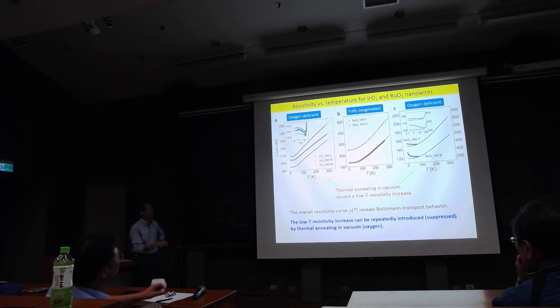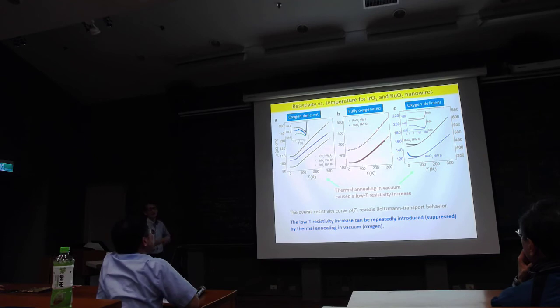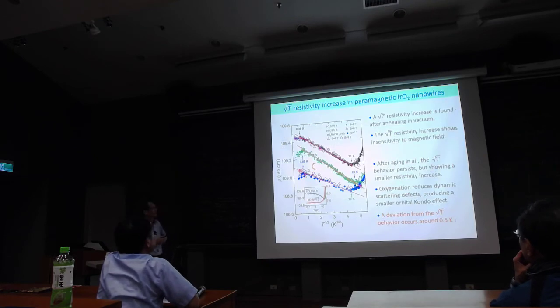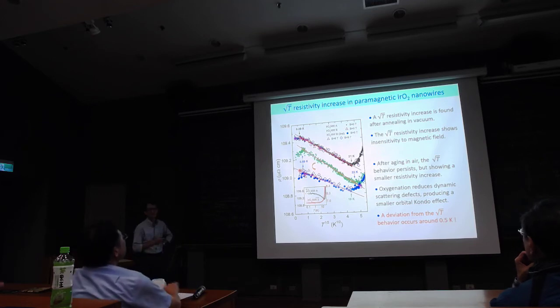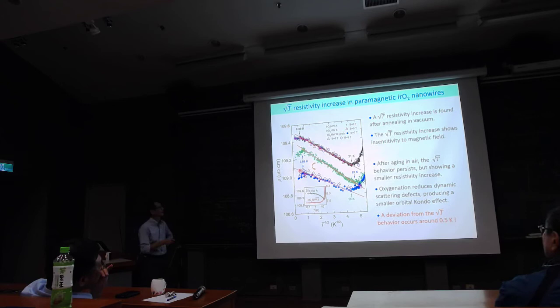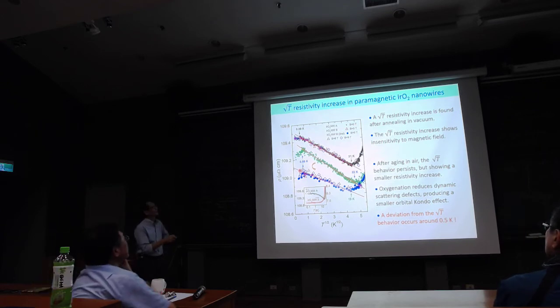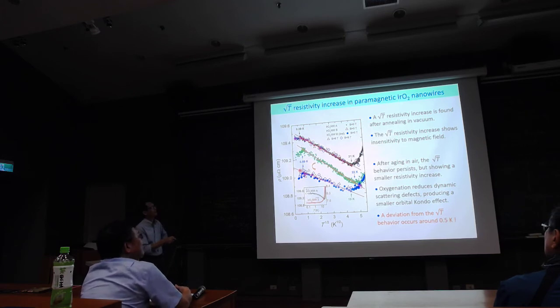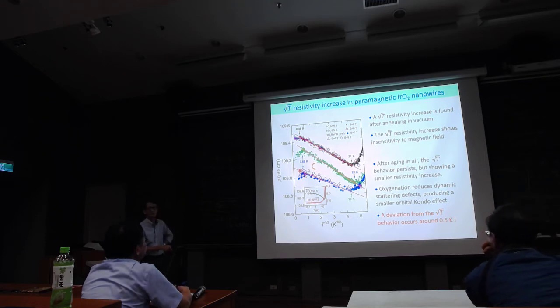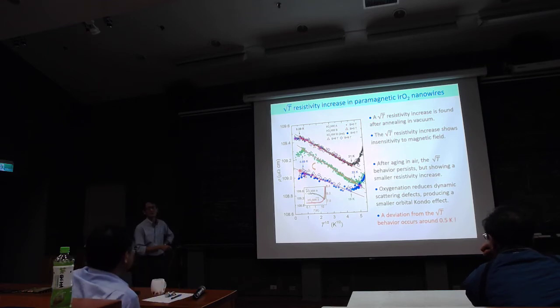So by controlling the oxygen vacancies, we can have Kondo resistivity or no Kondo resistivity. And what is most important today, maybe, is this figure. So in iridium dioxide nanowires, note that here is the square root of temperature. Because theories tell us that if you have this kind of two-channel non-Fermi liquid behavior, it should have some kind of square root T dependence.